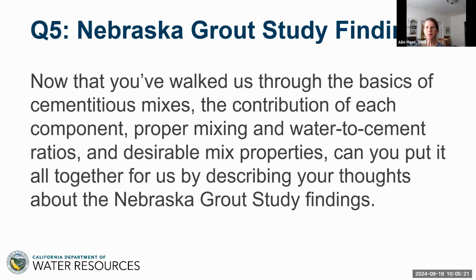Okay. When you started this review, Donald, we asked you to review the Nebraska grout study, since we were basing many of our limits on sealing materials in the uppermost portion of the well on those findings. In short, the Nebraska grout study observed bentonite slurries and neat cement cracking and desiccating in the unsaturated zone. Our reading of those findings was that those mixes had been negatively impacted by a wicking effect of the unsaturated zone, since findings were generally positive below the water table.